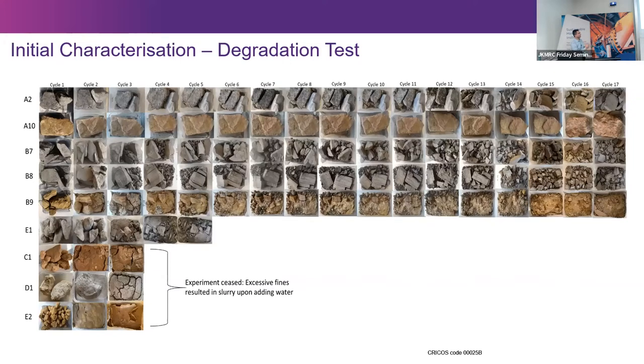until there's a degradation of rock. And we monitored the degradation of rock. And you can see some rocks are highly resistant to weathering, whereas some would just turn into very fine materials. For example, C1, D1, and E2, the bottom three, have just disintegrated after three cycles, compared to A2 and A10 on the top, where the rocks are still intact, even after 17 cycles, 17 months of sitting in water. So this tells us how important the breakdown is and how that would affect salt leaching. So that was also part of our degradation.